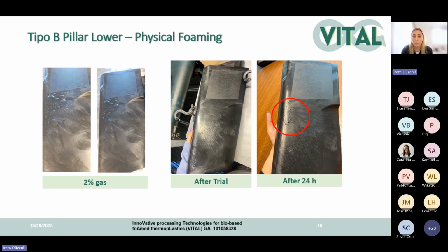We also tried to adjust the gas amount in the process and also some temperature settings. When we use 2% gas in the physical foaming process, you can see some big air bubbles on the surface. And these bubbles increase after several hours. Like in these examples, just after the trial there is no air bubble on the surface, but after 24 hours we can see some bubbles in the same parts. And we believe it's because the machine is too big for our molds. Our mold needs a lower capacity injection molding machine. And now we want to make sure whether this statement is okay or not.